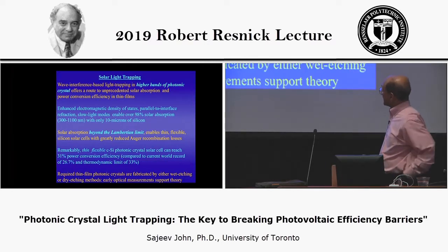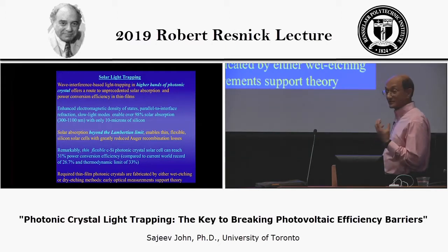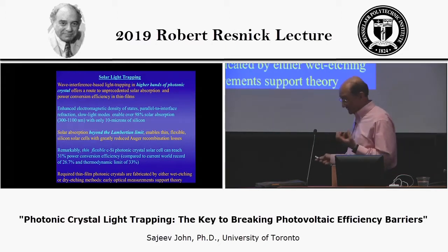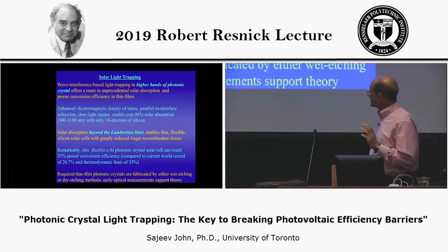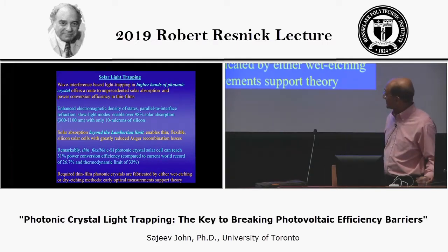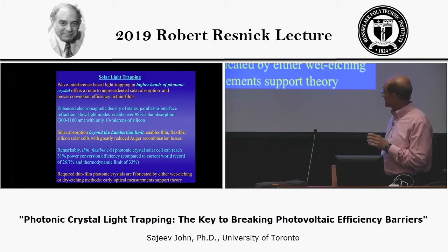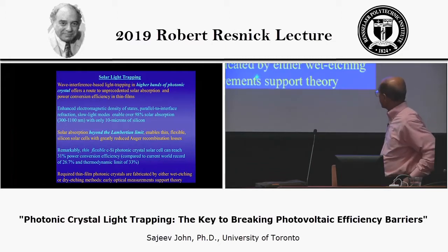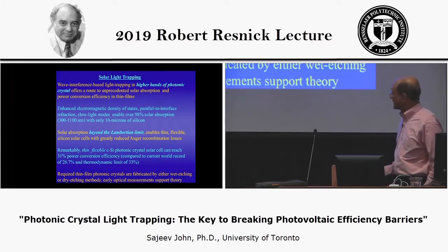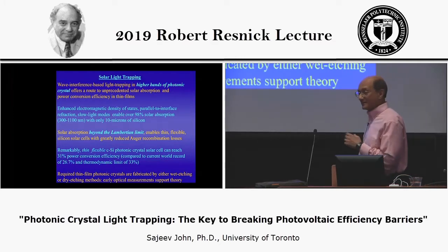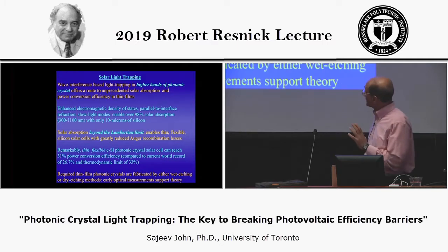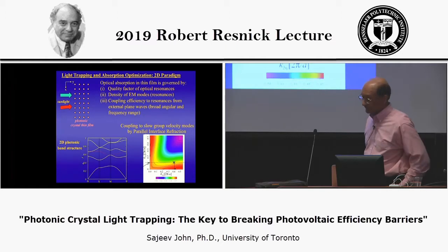In this case, our theoretical prediction suggests that it's possible within a realistic structure using experimental parameters for these recombination rates to reach up to 31%, compared to the current world record of 26.7% and the thermodynamic limit of 33%. And so some of these structures have already been fabricated either by wet etching or dry etching methods, and at least the optical part of the measurement seemed to agree with what we predict in terms of the amount of optical absorption that would be possible.